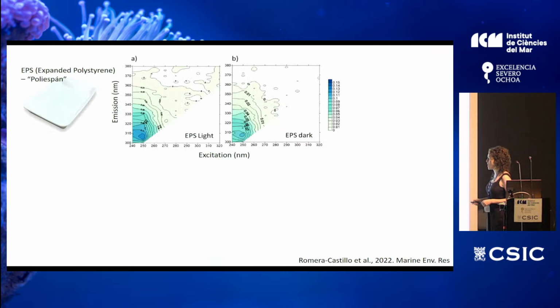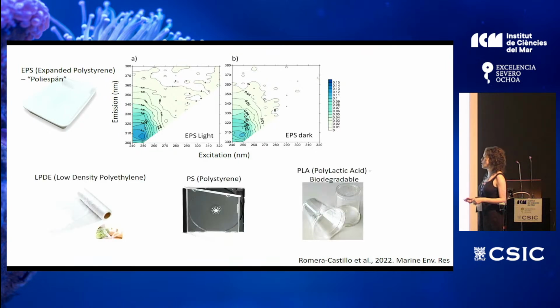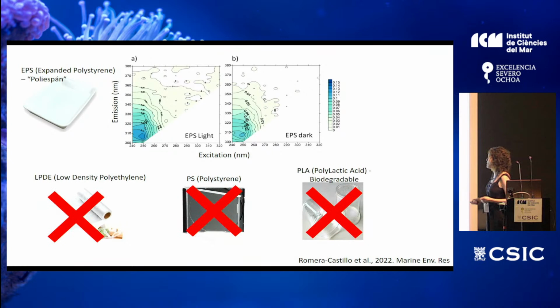So here we have the excitation emission matrix of the expanded polystyrene. This also shows a fluorescent signal here, also in the area of the proteins. In this case, the irradiated leachates were not lower in intensity than the dark ones. So probably the material released by the EPS was not that easily photodegraded. Regarding the other plastics, we found a fluorescent signal, but we didn't find a clear peak like this. So that's why I'm not showing these matrices. Probably because the new plastic is releasing a smaller amount of this fluorescent material. However, the EPS is a plastic that is faster leaching, and probably that is why this fluorescence is present.